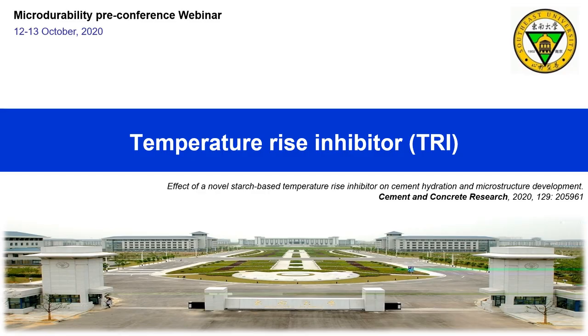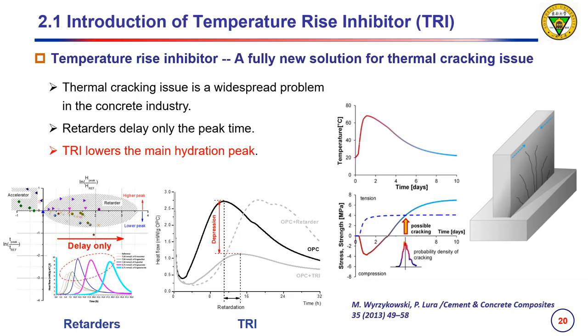The second part is the temperature rise inhibitor. This part is done by my PhD student, Yan Yu, who is co-supervised by Professor Karen in EPFL. Thermal hydration is an exothermic reaction. Temperature gradient may build up in mass concrete, leading to thermal cracking. Retarders delay only the appearance of a main hydration peak, which does little to help solve the thermal cracking issues. A novel admixture named temperature rise inhibitor, TRI, brings a new approach to solve thermal cracking by controlling the exothermic process during cement hydration.